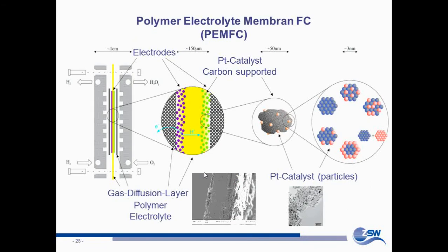So essentially what we're doing, we are making tiny little nanoparticles of noble metals, sometimes noble metal alloys, as we learned that they are to a certain extent more active or more robust than the pure platinum. We support them on a conductive support. Typically we support them on a carbon base, and then we integrate them into a couple of micrometer thick layer on top of the electrolyte. We have the electrolyte, and the other side it goes right back.